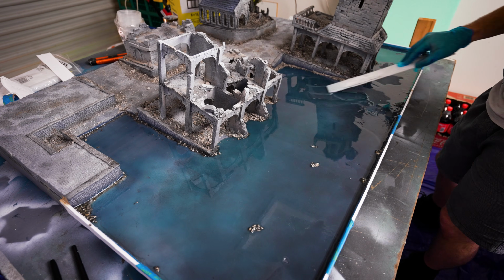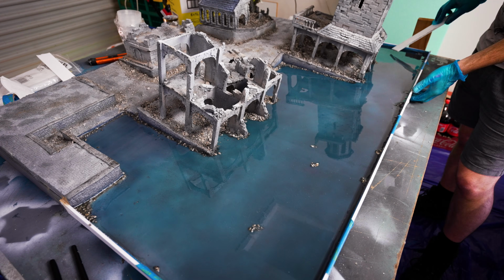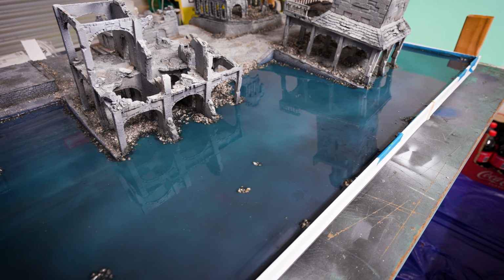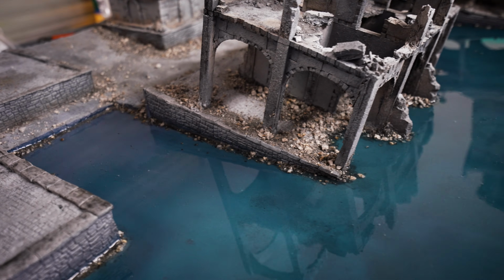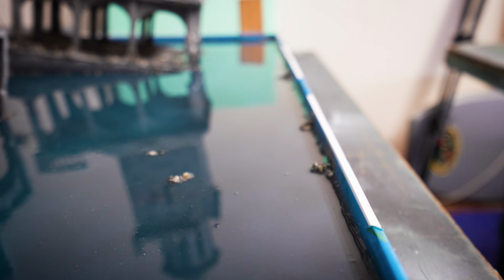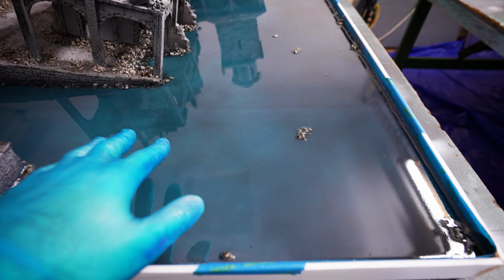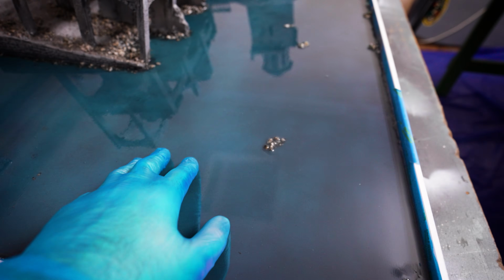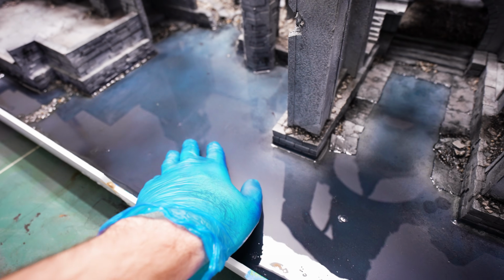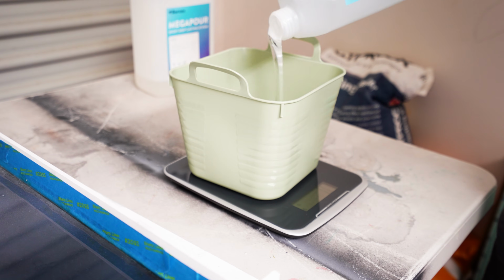Then about 16 hours later, that foundation was firm to the touch, and we officially have that base layer of about 3 millimeters down all over the board with no leaks. I'm absolutely flabbergasted. The epoxy resin seam has done some huge work for us. Now it was time to start mixing some bigger batches.